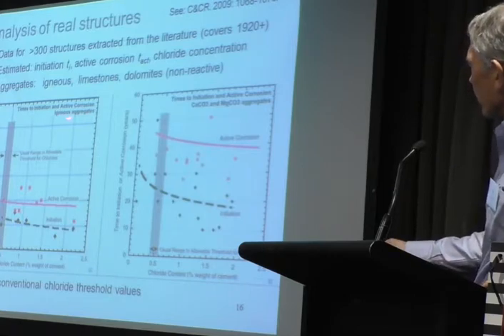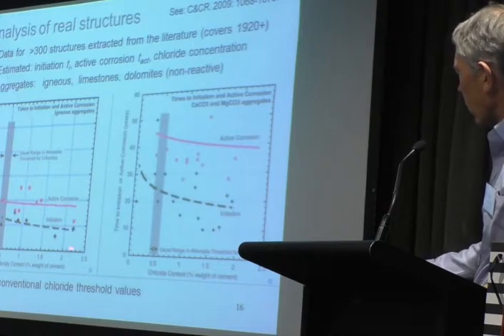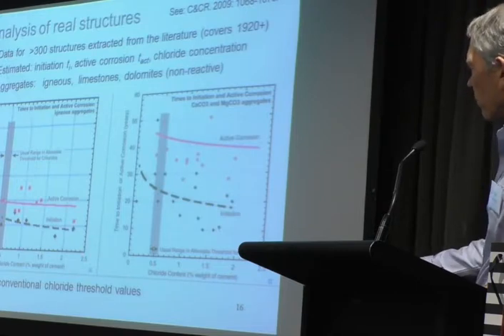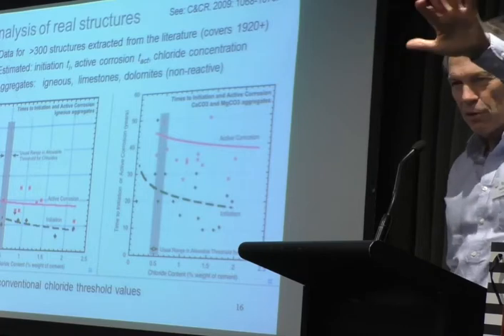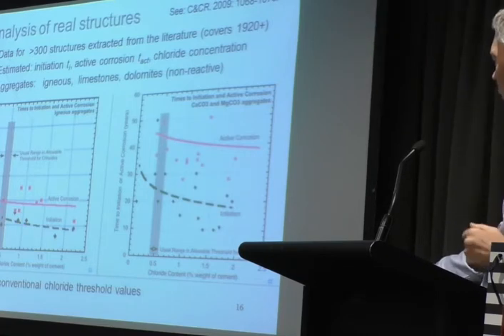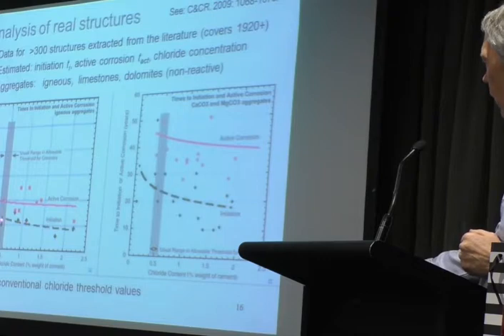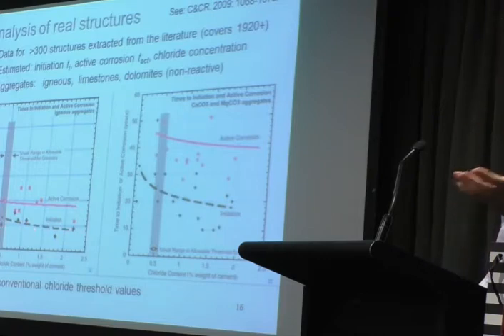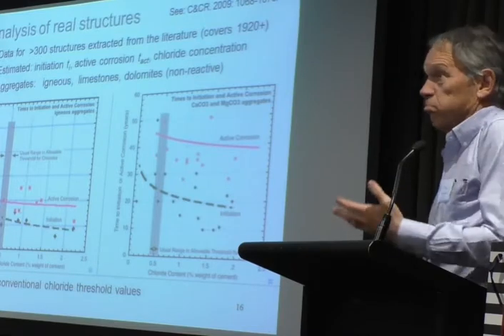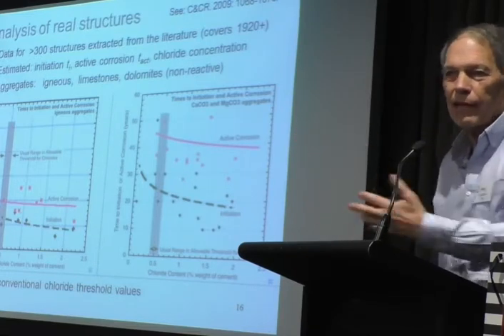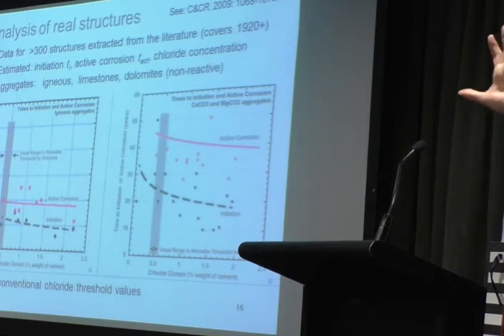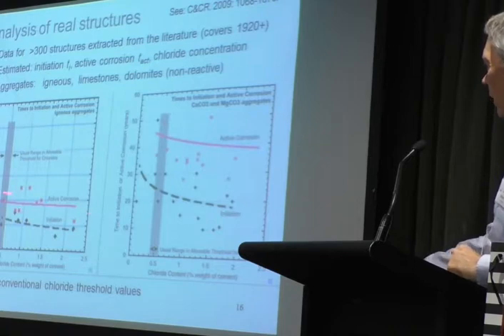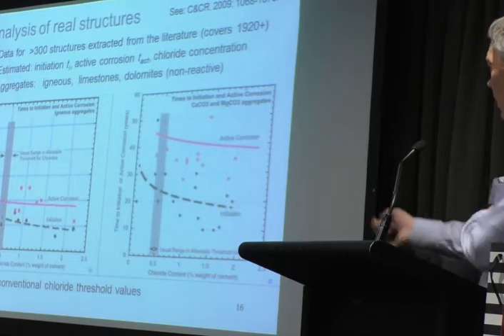And on that side, I've got the results for igneous aggregates. So we've got here chloride content, and this is pretty fuzzy. I mean, there's a fair bit of fuzziness in that result, but that was our best estimate. And also the two times that I've got here: the time when we thought initiation occurred, typically from reading reports when they first saw signs of some sort of rust staining, to say that, yeah, something's going on, but there was no significant damage to the structure. And then later on, they reported in later reports that something serious was going on. Now, these numbers are somewhat rubbery.